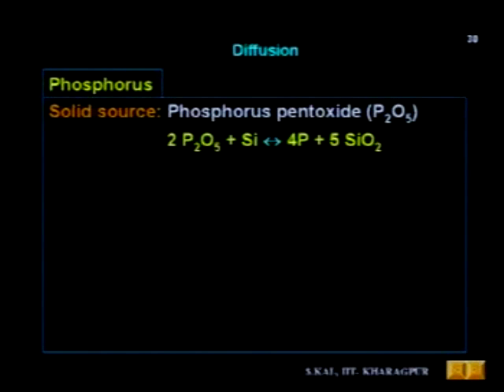In phosphorus, again we will see the reactions for the solid source, liquid source, and gaseous source. The solid source of phosphorus is P2O5, known as phosphorus pentoxide. Phosphorus pentoxide reacts with silicon and forms the phosphorus atom and silicon dioxide. So 2P2O5 plus 5 silicon will give you 4P plus 5 SiO2, and this phosphorus atom will diffuse into silicon, and the silicon dioxide formed at the surface is removed in hydrofluoric acid. Here, unlike boron, phosphorus will not form a stain, and this SiO2 along with a few phosphorus atoms can easily be removed in hydrofluoric acid. You don't have to go for LTO.